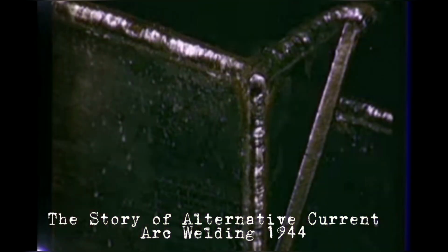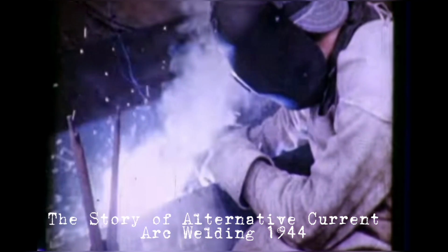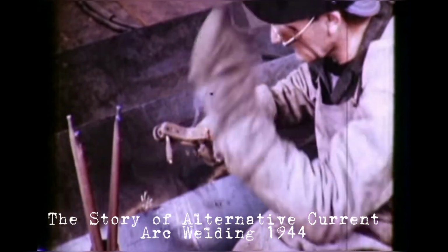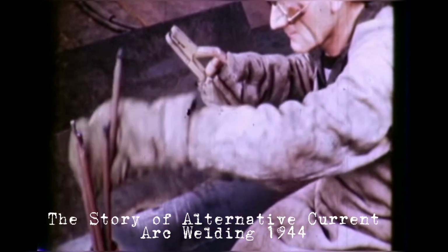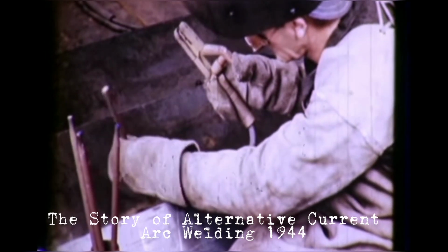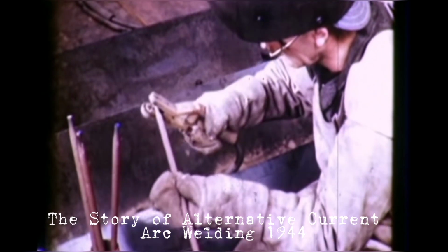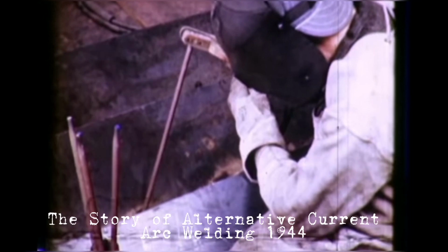In flat position welding, much of the time and effort lost in frequent changes of electrode can be saved by using large diameter electrodes. With alternating current, 3/8-inch diameter electrode can be used with high currents to produce smooth, uniform welds.